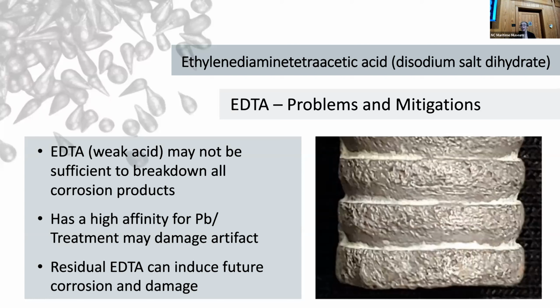It also has high affinity, as sort of the original sin of EDTA and why it was not really used as a health supplement anymore, is that it is very, very good at binding to those metal cations, and lead it has a very strong affinity to. So you can very easily overdo it if you use too high a concentration. If you leave it in there too long, you can remove too much material, and you can basically start stripping lead off from the surface of your artifact, which defeats the purpose of trying to preserve that surface and make it more legible.